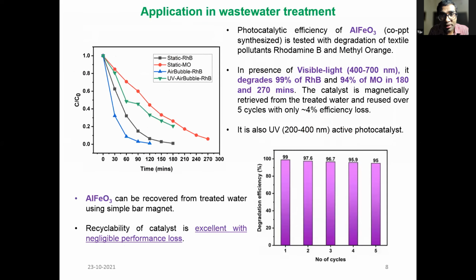So we have been deploying it for wastewater treatment. And in fact, it seems to be active both in visible as well as ultraviolet light. It seems to work quite well for both anionic and cationic dyes of the kind that we tend to be worried about in our country. And you will find that the recyclability of the catalyst is excellent.